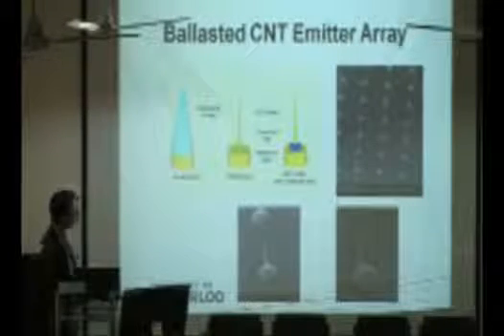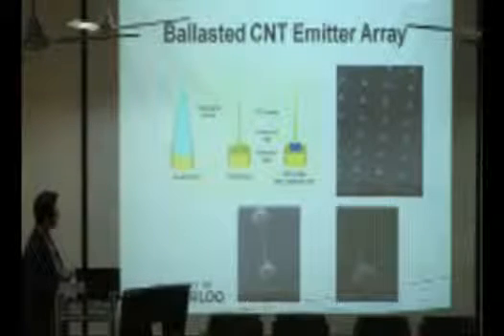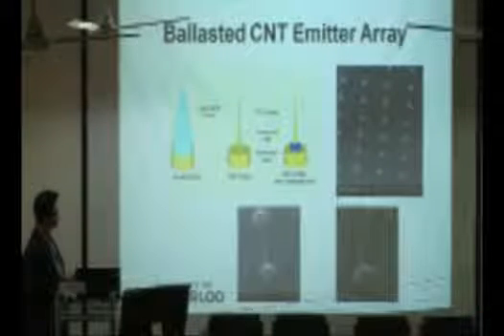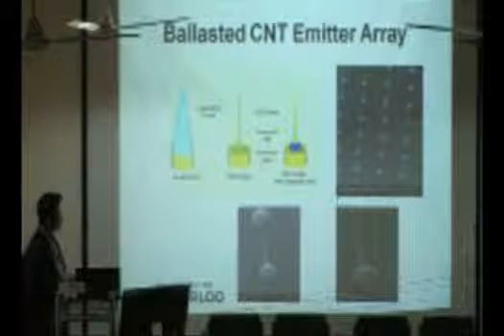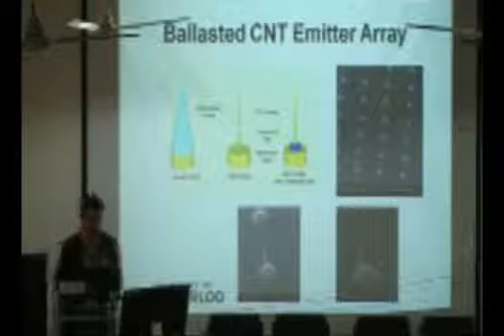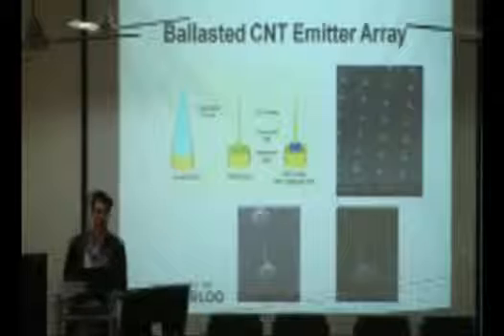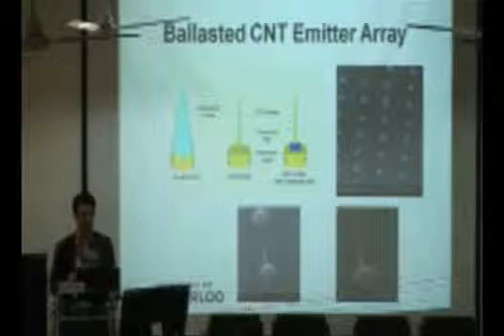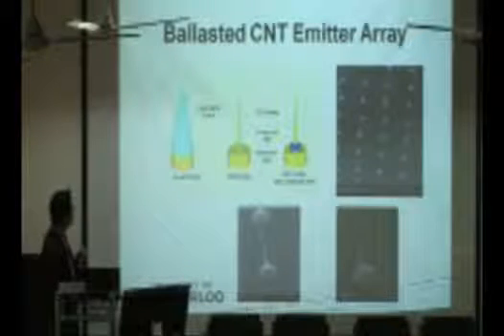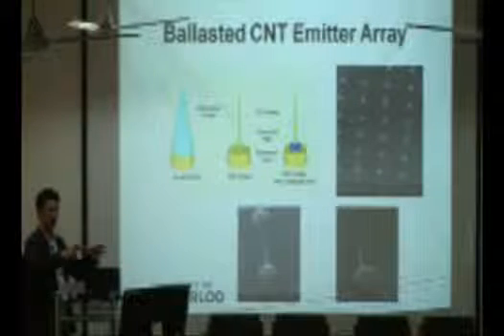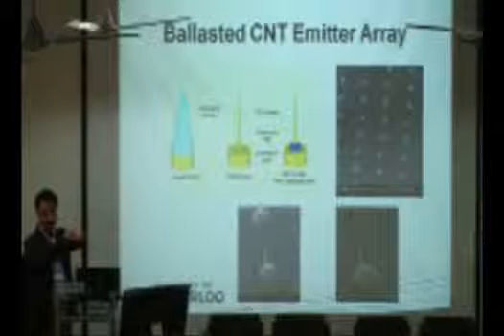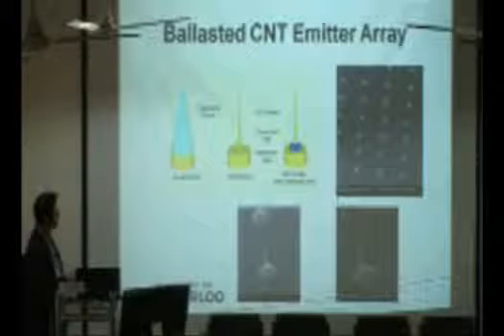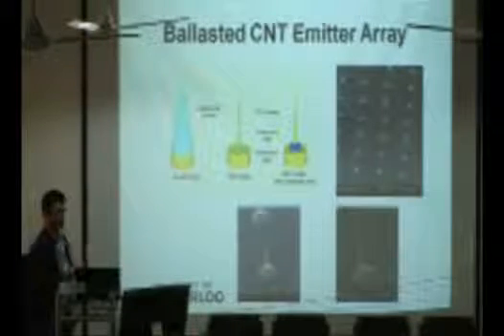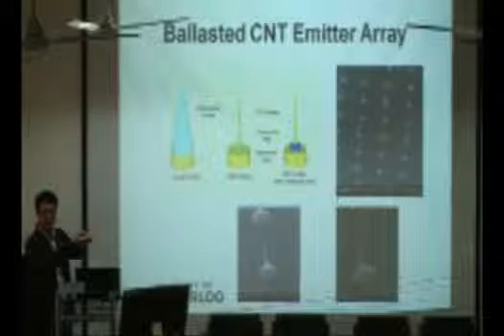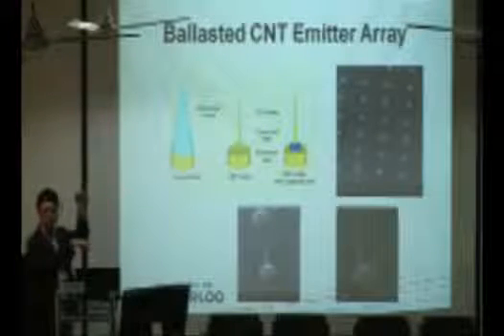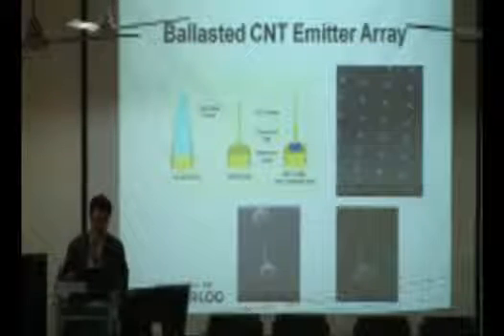Now, this is what we have done in the lab. This is a field emitter. This is a single strand of CNT. This is a hybrid structure we have come out with on a substrate, because another engineering challenge that we have to come up with is we are trying to allow CNT to act like a field emitter. And the challenge is, a field emitter is a solid structure with a really broad base. So this broad base has a really tight connection with the bottom substrate. But with the CNT, because it's a really thin hollow tube, the contact between the CNT and the substrate is really minimal. It is actually very easy to pull the CNT off the substrate. Now, this is an engineering challenge that we have to overcome.